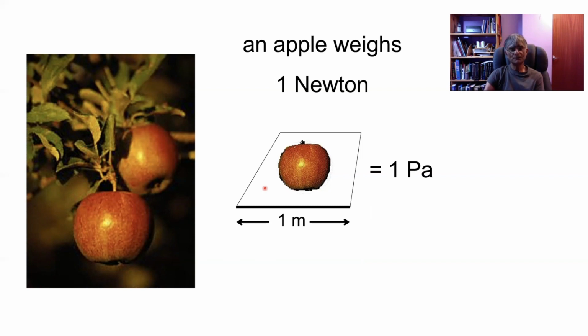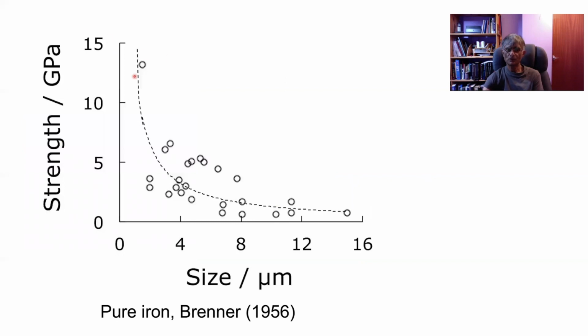Now, back in 1956, a strength of the order of 14 gigapascals was already achieved. Okay, and this is in pure iron. So these data come from single crystals of pure iron, and this gives you the size of those single crystals. Now, you can see that there is a dramatic decrease in strength as the size increases. And this is because, you know, if you make your crystal small enough, then it's hard to find defects in it, and defects tend to reduce the strength. So by defects in this context, I mean, for example, dislocations.